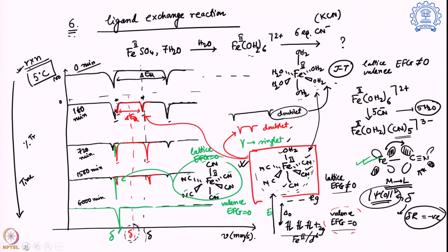So over here now you can see that the whole system is showing me that there are three different components working there. One is the beginning one, then there is the 5 water molecules replaced by 5 cyanide molecules one, and the final one, the all hexacyanide sample. So this is, I can see over time how it is behaving, and I can see this 5 cyanide water molecule bound system, this red one is the intermediate one, which slowly also transfers to the final product of the hexacyanide one. So over here it is showing that Mössbauer spectra can show you this system. So over here I am just summarizing the information that we found.